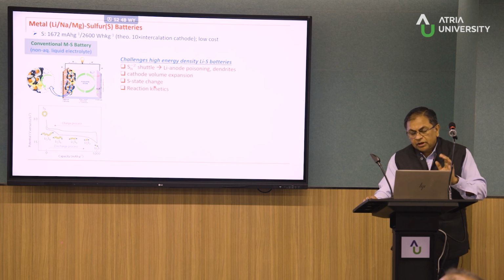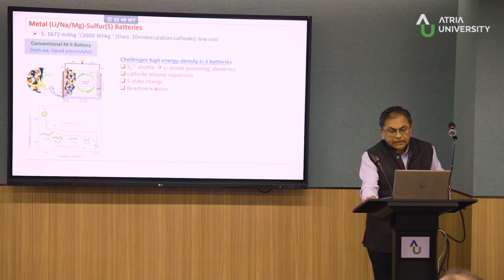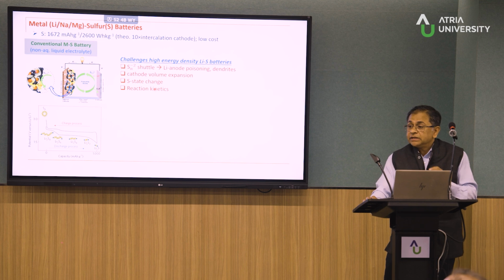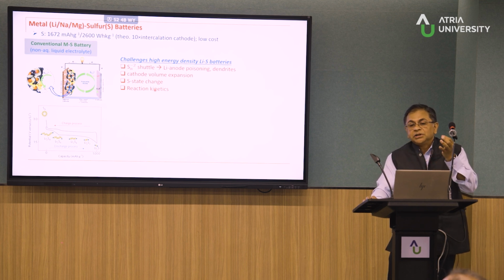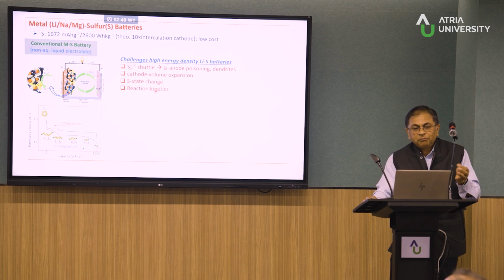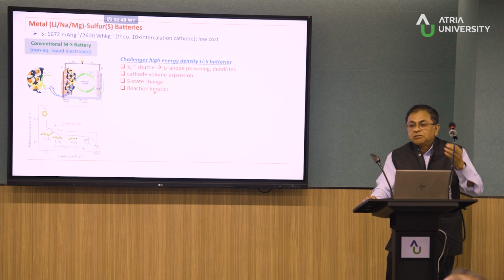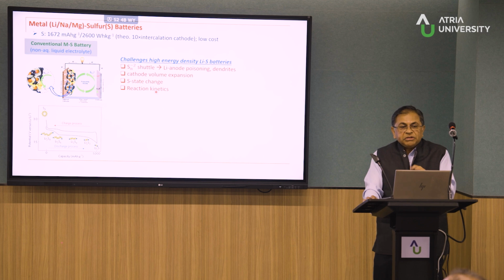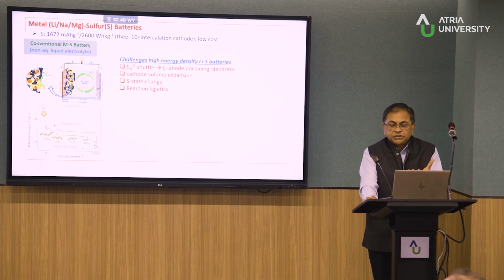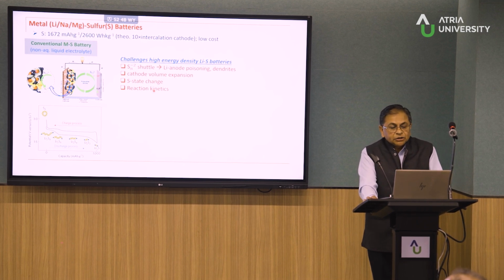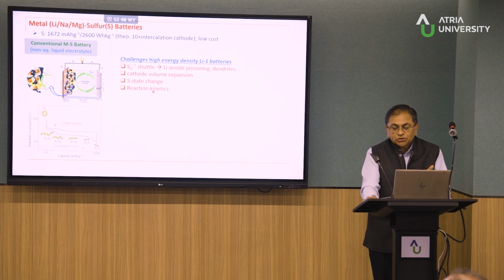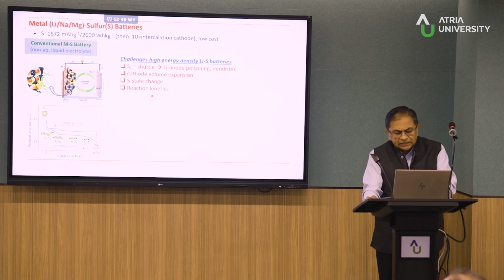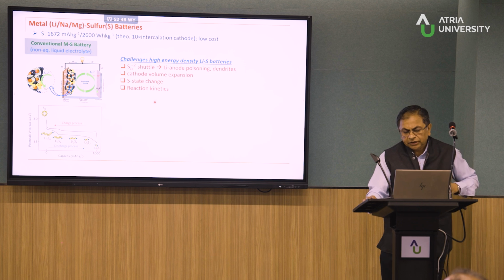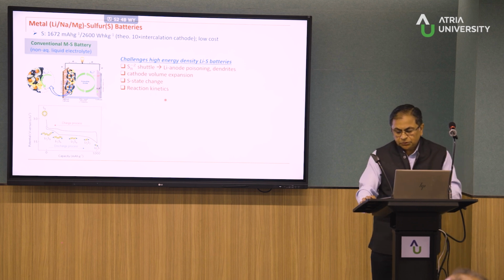But since we have been working on this for almost a decade now, we have found other problems. There is a change in the state of sulfur, which many don't even know. You start with sulfur in the crystalline state, but if you just keep this in air mixed with some high porosity carbon, it changes completely to an amorphous state. So that shows a very different kind of cycling. We had very interesting investigations with reaction kinetics and so on.